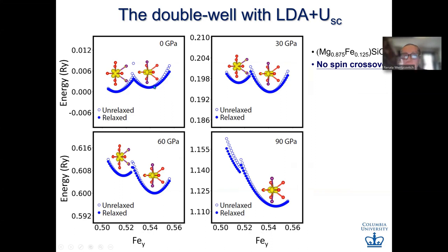So, as I'm saying, like in the high spin, low spin case, you have quadratic curves, energy surfaces here, and the ions are separate. So they can coexist in a situation like this. That's what the experimentalists are seeing in Mössbauer: two kinds of high spin iron on different sites with minority electrons on different orbitals.